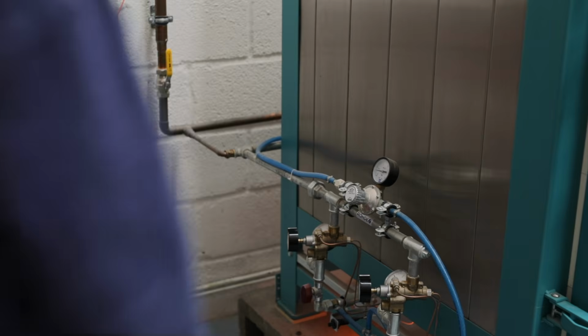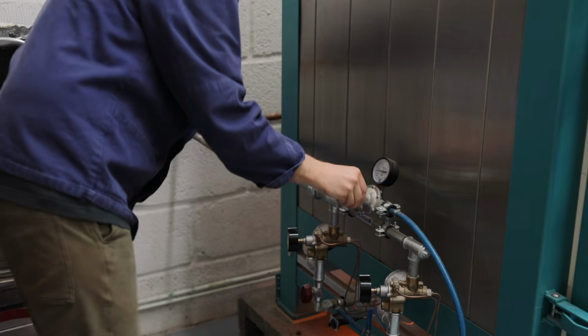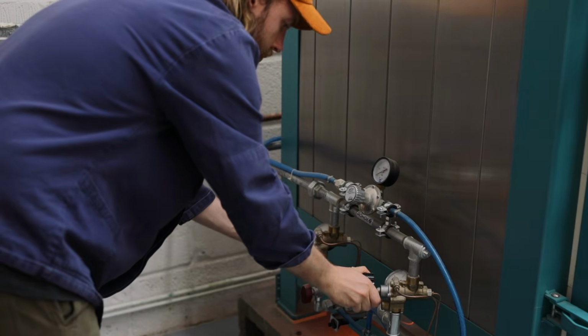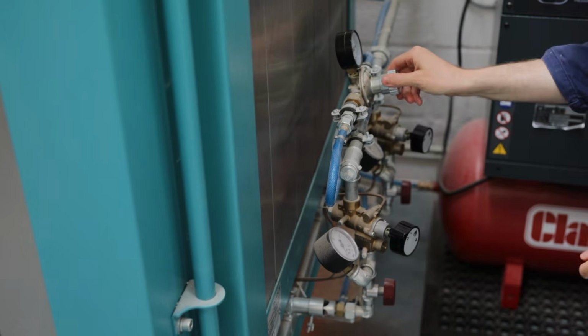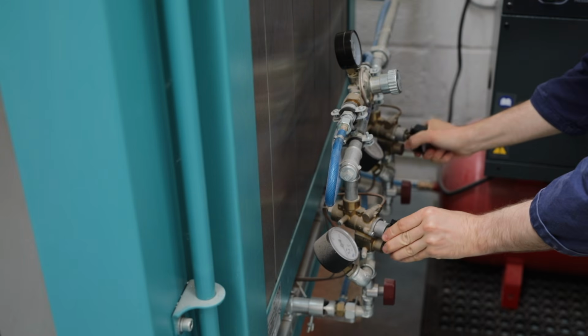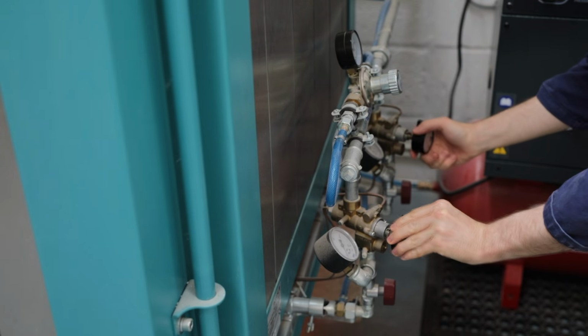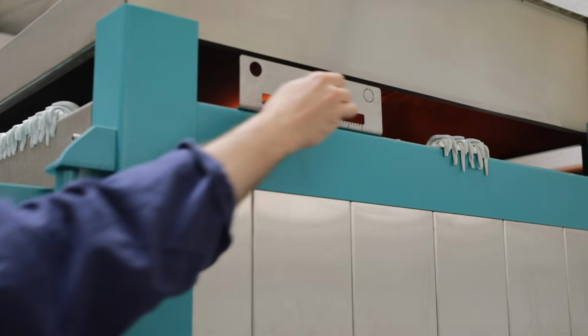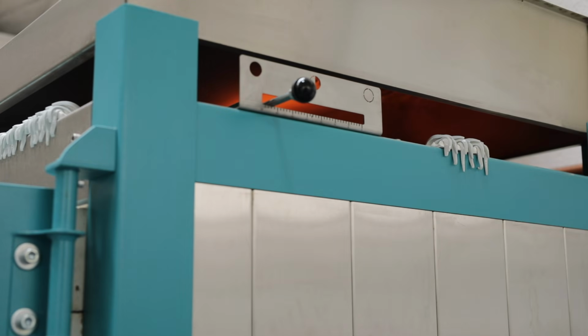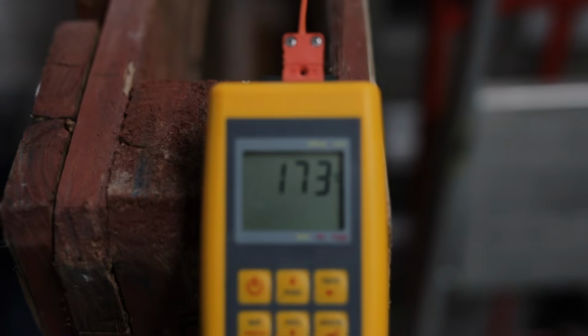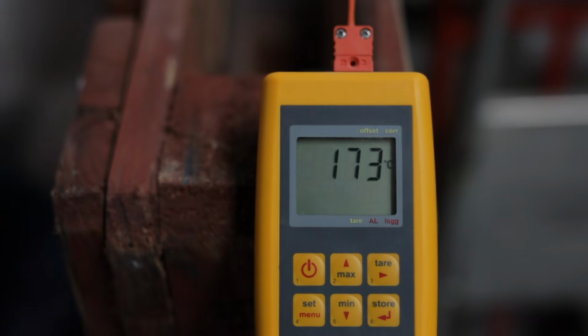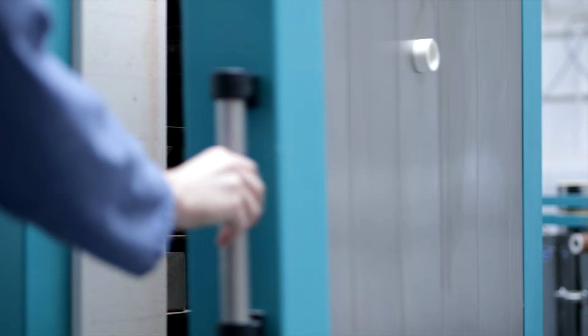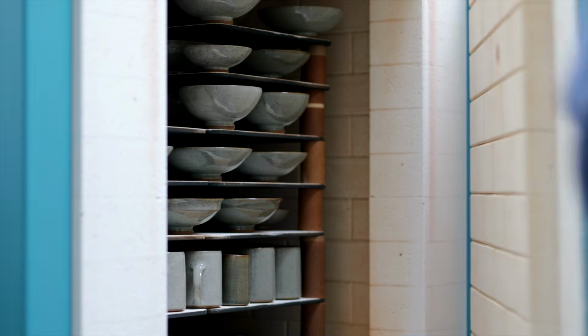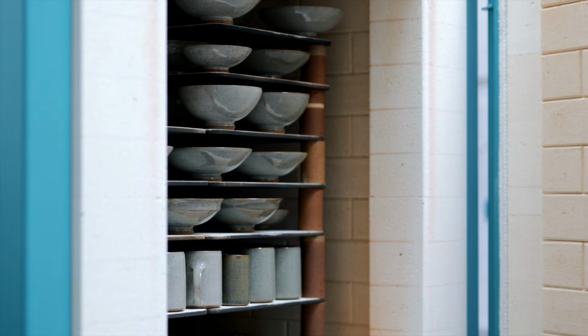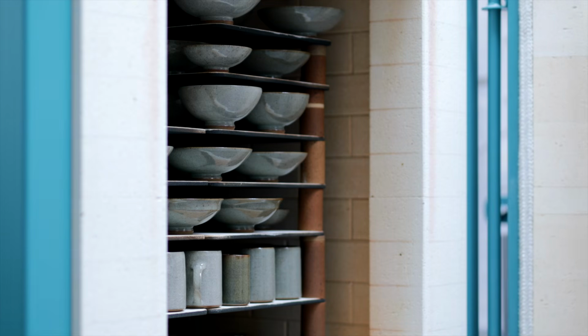Once the cones inside have all bent over sufficiently, I turn the mains off first, and then each of the 4 burners and the air. From this point, I'll crash cool the kiln down to 1000 degrees Celsius, which I do by opening the damper fully and removing the bungs from the spy holes in the door. This only takes about 30 minutes, and then I'll seal the kiln up properly, and a few days later, it's ready to unpack. I crack the door open, revealing pots that are now greens and blues and whites. They're as hard as stone, and are encased in glass.